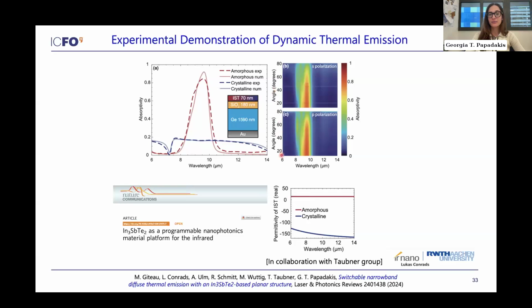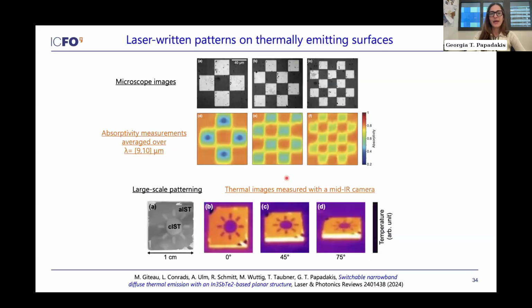Here you can see the angle dependence of this. So this is a diffuse source of IR light. And here what you can see is that we went ahead with a laser and created patterns, these chess patterns, where the top material is IST, and in one phase it's in the amorphous phase, and the other is in the crystalline phase. So these are the actual microscope images.